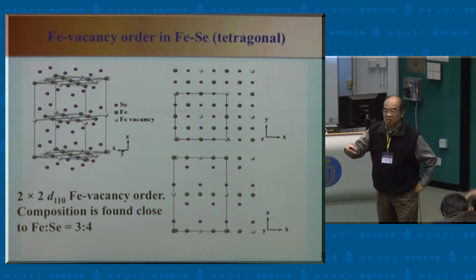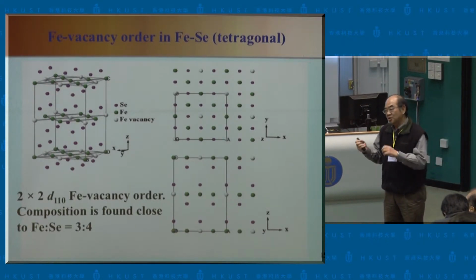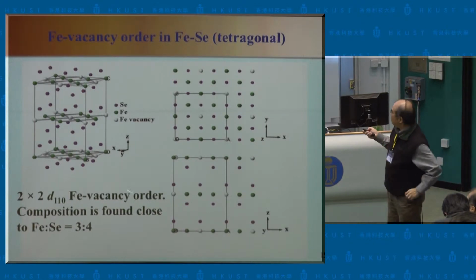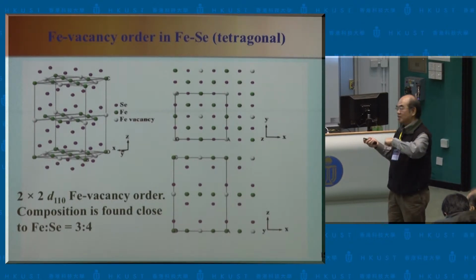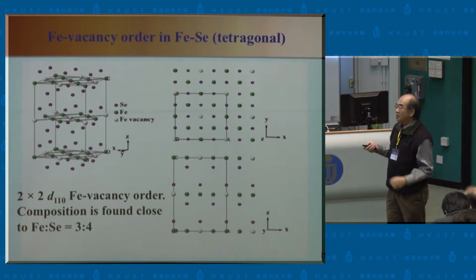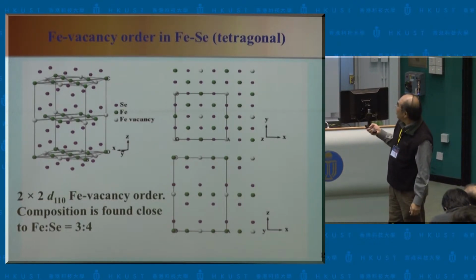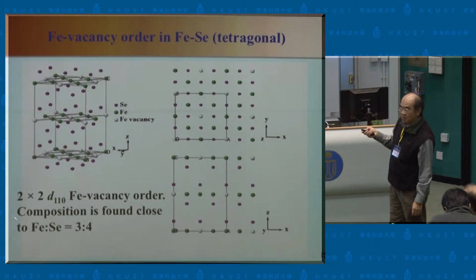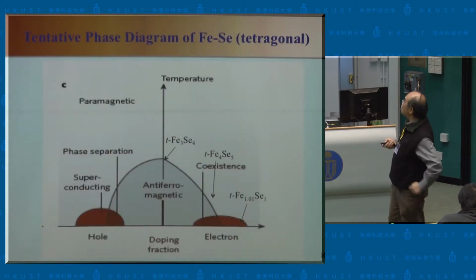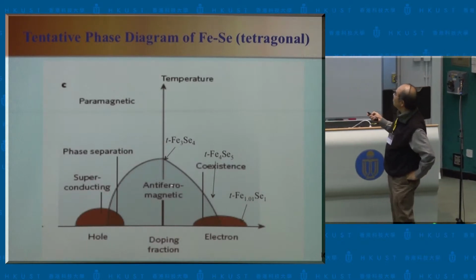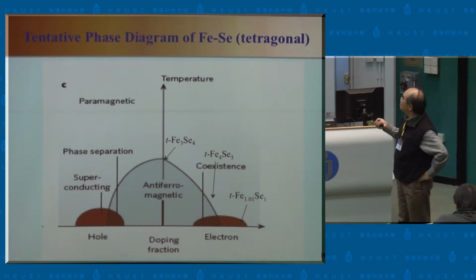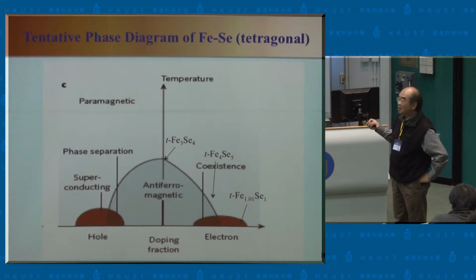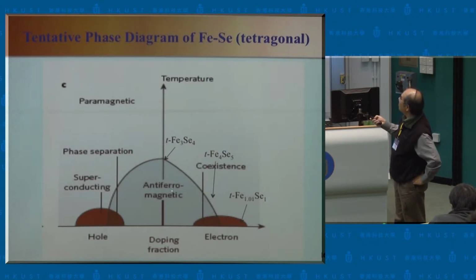We are doing this in more detail now, because we can do it the other way, for example, from 2,4,5, then extract the potassium out to make it a pure iron selenide, and so on. Okay, so all these results indicate this iron actually is deficient. So we are now proposing a new phase diagram, which needs to be studied in more detail. That we probably have a parent compound close to this tetragonal 3-4, which is magnetic,